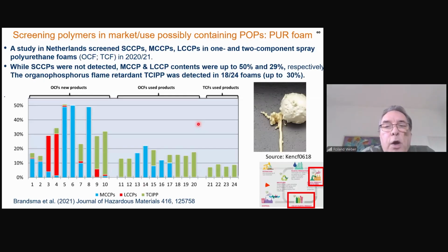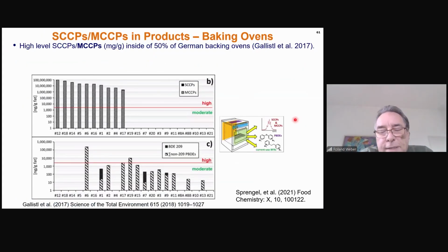You see here a study on polyurethane foam used also in new buildings. In the Netherlands, they screened also for chlorinated paraffins, and they found that a range of foams contained up to 50% of medium chain chlorinated paraffins and up to 29% of long chain chlorinated paraffins. Additionally, organophosphorus flame retardants are contained, and these materials then are also gassing out these additives and finally contaminate the indoor environment with high levels in house dust.